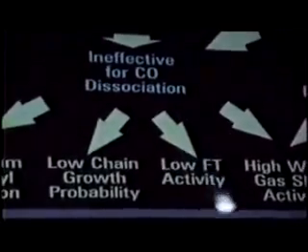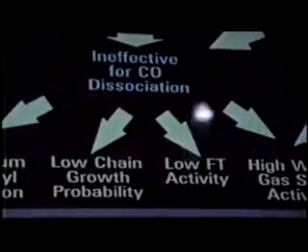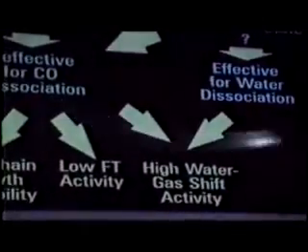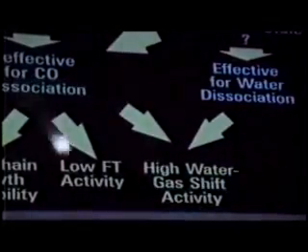If you cannot dissociate CO effectively, you have low Fischer-Tropsch activity and the reaction which does not require CO dissociation, which is water-gas shift, is enhanced.